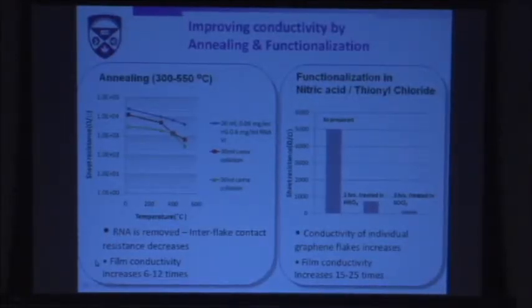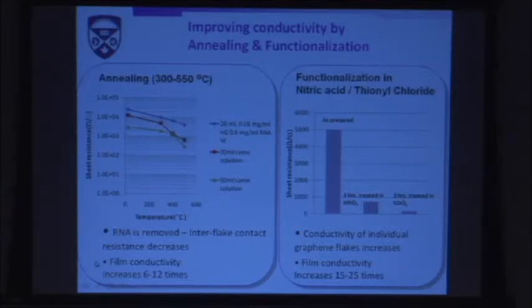These films, in these cases, since I have nanocomposites, the conductivity of my films also depends on the RNA that remains in the junctions. RNA is a pretty insulating material, right? So I have to remove it. One way is to heat up and reduce RNA literally to ashes. It goes away, and in fact the sheet resistance, the inverse of the conductivity, goes down, and the conductivity improves pretty much, even better than graphene oxide, so that works, just with temperature to get rid of RNA at